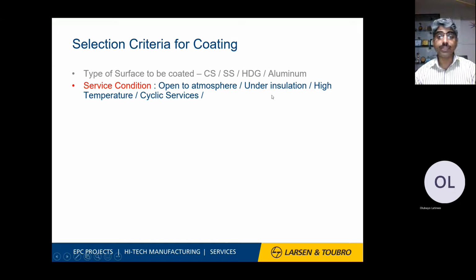For CUI, there is a special NACE standard, NACE SP0198, which says how to do coating for under insulation applications or under fireproofing applications. High temperature is again a challenge because the maximum upper temperature limit is 650 degrees C for any paint selection. Beyond that there is not much corrosion because there is not much water phase available for reactions. So even carbon steel we can put without coating, and no coating will have life at that temperature.